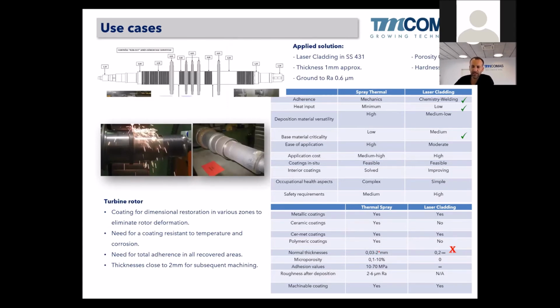Another use case, in this case, we have a turbine shaft that was bent. I don't know if you are able to see here, but the bending in the ends of the shaft was more than 1 millimeter. So the customer asked us to straighten this rotor. We decided to make a laser cladding of all these journal areas, these shaft areas, strengthening the shaft by cladding and then machining. So we have machined off all the seal areas in this area, and then we have clad the whole shaft.